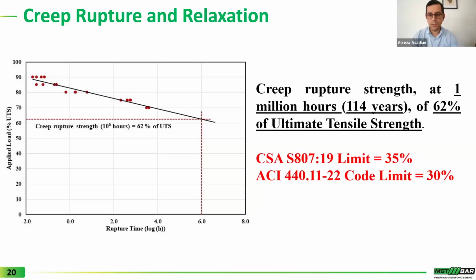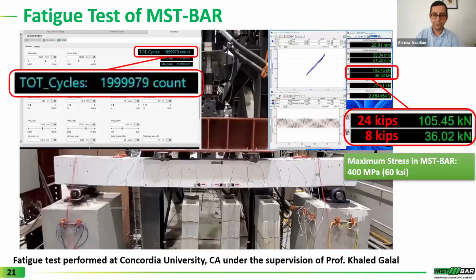And as you can see in this graph, the creep rupture strength at 1 million hours, or 114 years, for MST bar was around 62% of Ultimate Tensile Strength. And for your reference again, the limit in CSA S807 is 35%, and the limit of the ACI 440.11 code that is used for design of GFRP reinforced concrete is 30%.